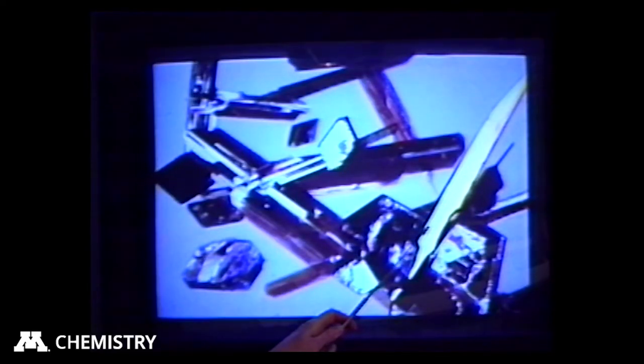Here is this bright gold crystal that I told you about. It just looks like a gold mirror. Here are the red crystals that I mentioned a minute ago. And in addition, we have pyramidal crystals. And if you look carefully, and I'll show you some more examples of this in a minute, you can see a phase transformation taking place, where little black lines are starting to form, where a reaction is actually taking place. In addition, you see several different kinds of red crystals.